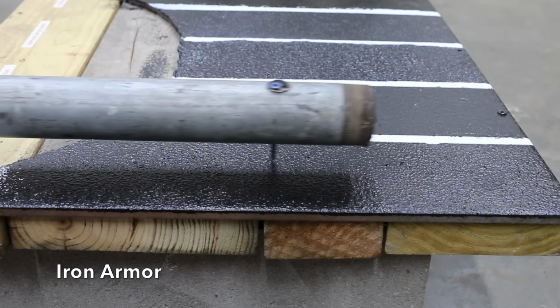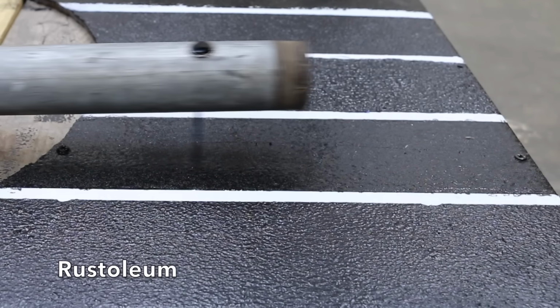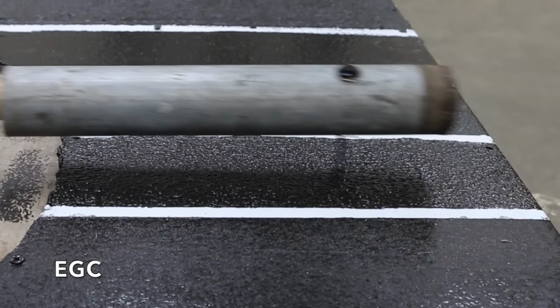Testing Harbor Freight's Iron Armor first. The screw left a fairly deep scratch in the Iron Armor, but the screw wasn't able to cut all the way through the bedliner coating. The screw left a scratch in Rust-Oleum, but the scratch wasn't as deep. EGC did by far the best yet. I had to use a microscope to even find the scratch.